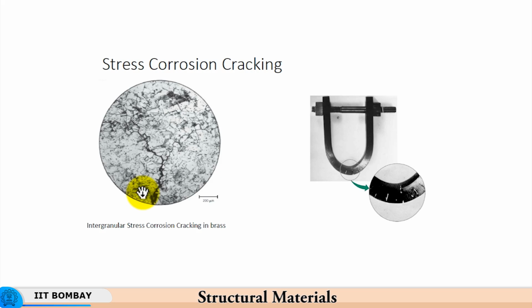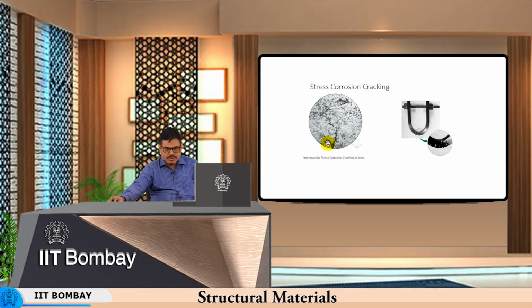For instance, here if you look at this, there is no corrosion. That is because this is cathodic with respect to this part. Here it is anodic because very high stress and very high deformation are present, so a large dislocation density is present, and especially on the outer surface there is energy of cold work, and therefore the material can be eaten away relatively fast. On the top surface you see there is no corrosion. Why? Because this has been subjected to compressive stress. When there is compressive stress acting on the material, you do not have any corrosive attack as such, but again, if there is more stored energy of cold work.